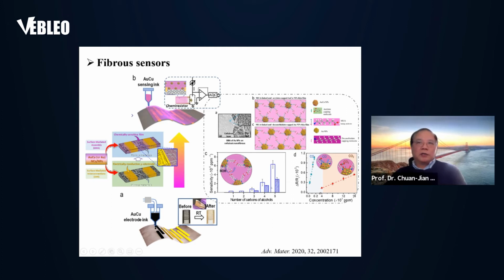When molecules, such as alcohol molecules, as illustrated here, different chains of alcohol, CO, CO2, enter the interparticle spatial confinement, they introduce intermolecular interactions. Those interactions change the electronic properties. Then we can detect the response in terms of the resistance change. So that's really one nice illustration demonstrating that nanoscale chemistry works very well for a fiber sensor.